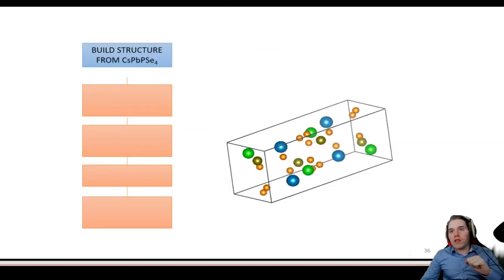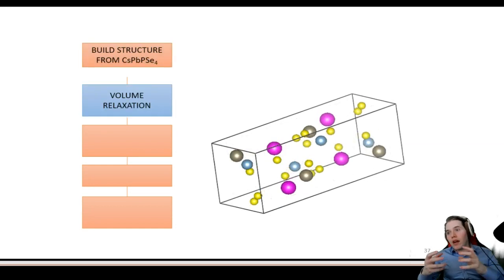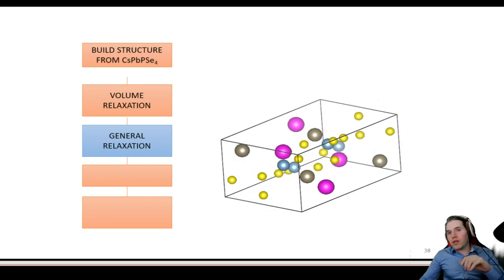So here's, for instance, this crystal structure of cesium, lead, phosphor, selenide. We replace the atoms, but because the atoms have different sizes, let's say pretend they are balls of different sizes, now the geometry is a bit wrong. So first we have to adapt the volume. Then we also have to let all these atoms move around a bit within the cell. And then this box will actually also change shape, which is quite complicated.